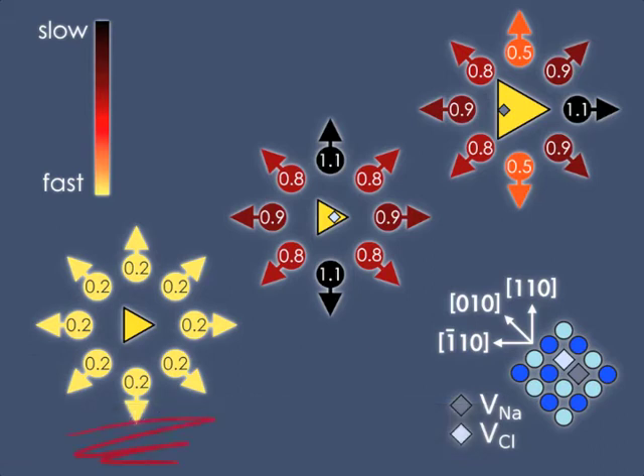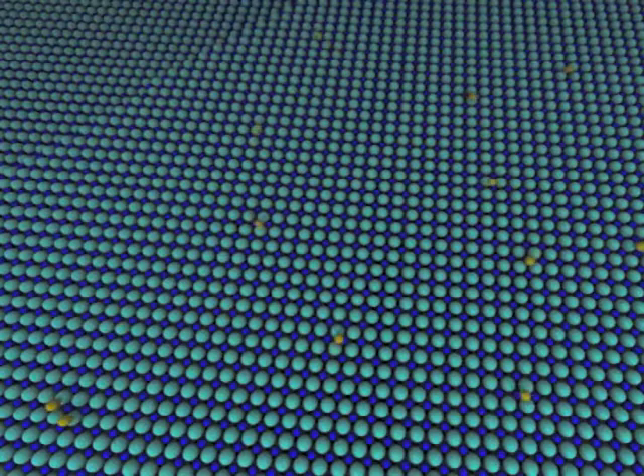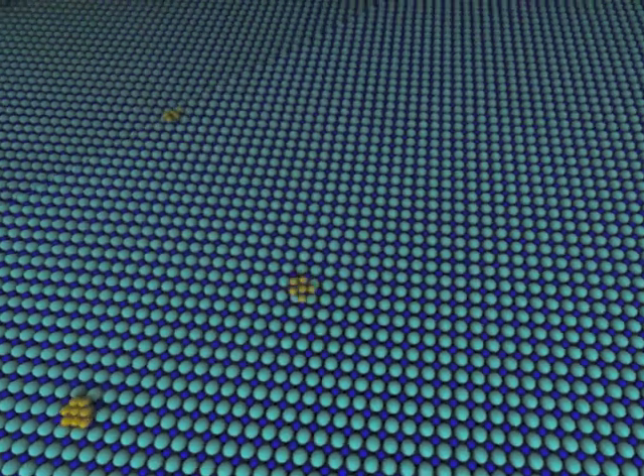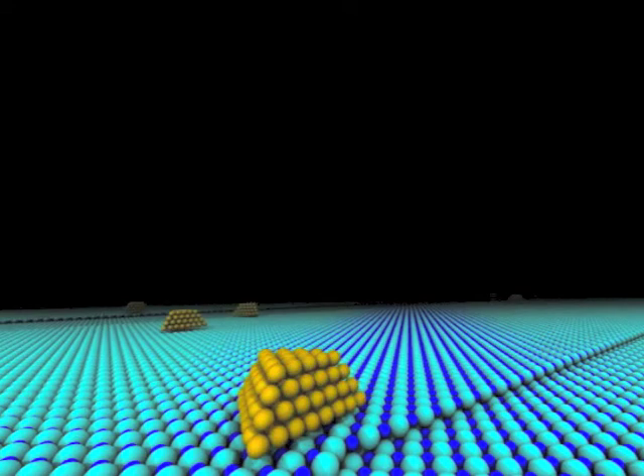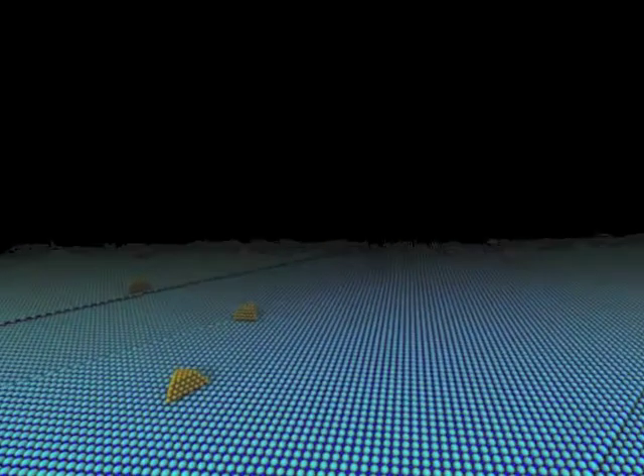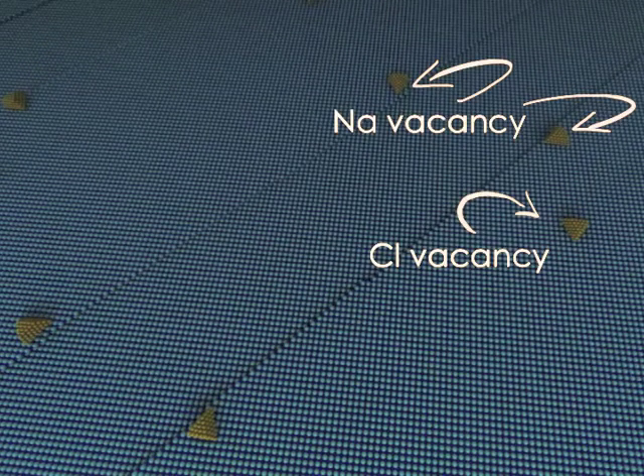On the perfect surface, gold is mobile, and on a sodium vacancy, it strongly prefers to move in the 110 surface direction. In the experiments, gold is deposited on a sodium chloride surface as atoms. The gold atoms diffuse around until they find vacancies, forming nucleation centres for the clusters. The common defect on the terrace is the chlorine vacancy, while the steps and sodium vacancies are more commonly found. This means that clusters that grow in different places should also behave differently.